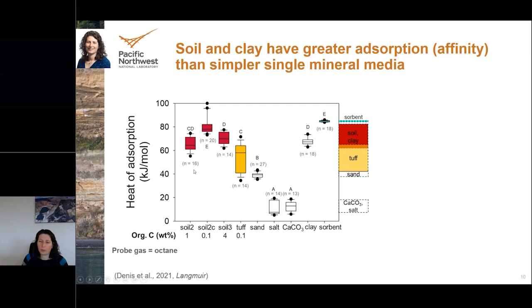And just to get you oriented with this plot, I know it's a lot of information, but for reference, the letters that you see above and below the box plots mark the statistical significance of our results. So boxes that do not share a letter are statistically different. For example, the salt and calcium carbonate down here with the lowest heat of absorption, they both have the letter A, which means they are not statistically different from each other, but they are statistically different from others that do not share a letter A. So all the other geologic materials are statistically different. We also made replicate measurements on multiple sample columns, and this figure provides a summary of all the individual measurements, which is noted by the N by each box plot.